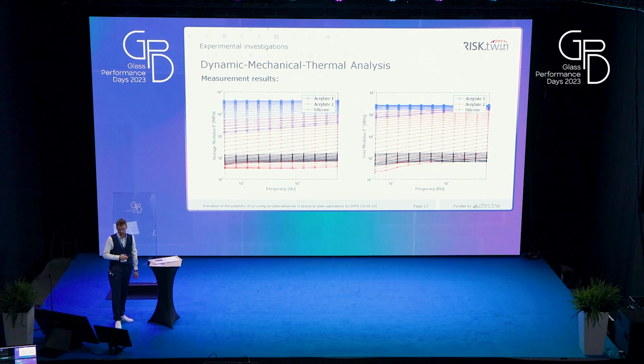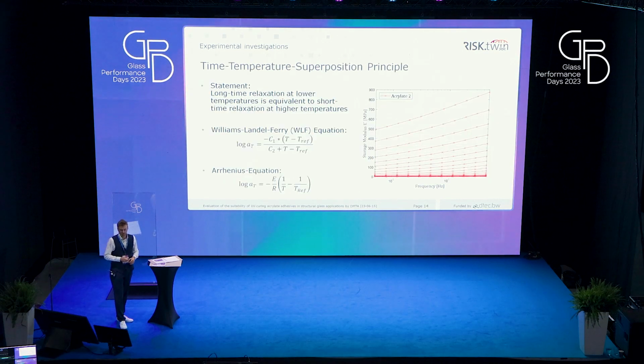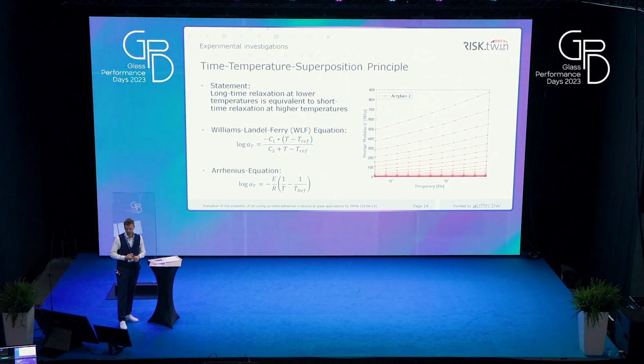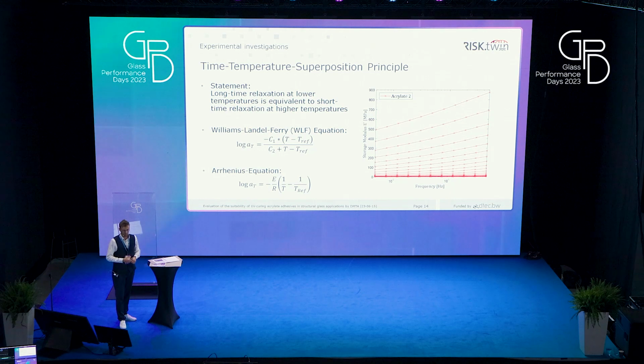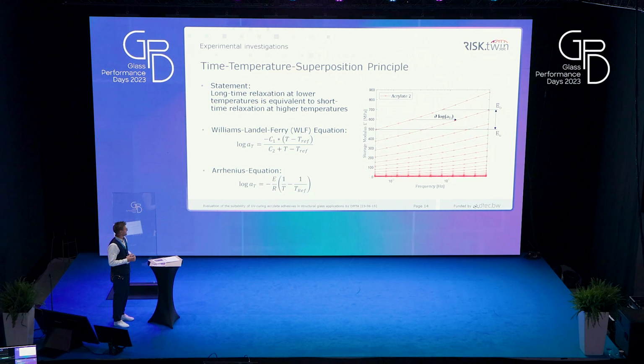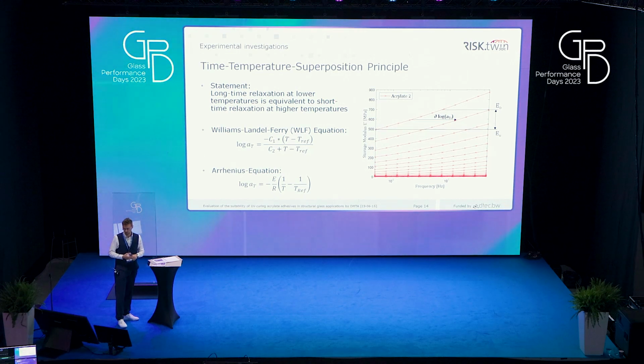With these curves now, we can make use of the so-called time-temperature superposition principle, which states that the long-time relaxation at lower temperatures is equivalent to the short-time relaxation at higher temperatures, which allows us to build a so-called master curve and get the results over a much wider frequency scale. You can imagine this by just shifting the curves to the next curve for a chosen reference temperature, which we chose to be 20 degrees Celsius.